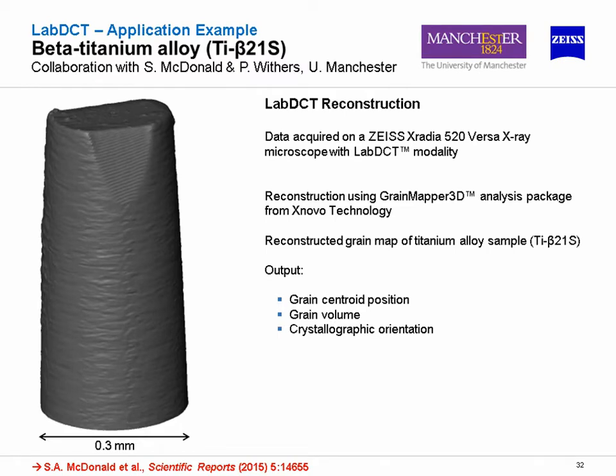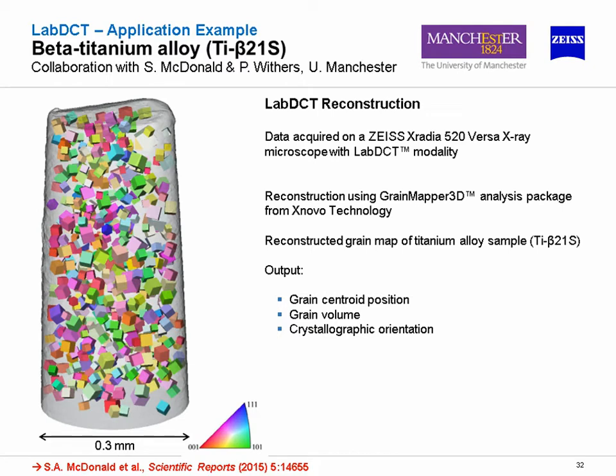Now, one of the first validation experiments was done on a beta titanium alloy, and here's what you would see in a conventional absorption scan. You don't see much information other than the exterior of the specimen, but we can now populate this after a DCT analysis with the rich crystallographic data. Those cube centers indicate the centers of each grain, the size of each grain by their size, and then the crystallographic orientation with their color.